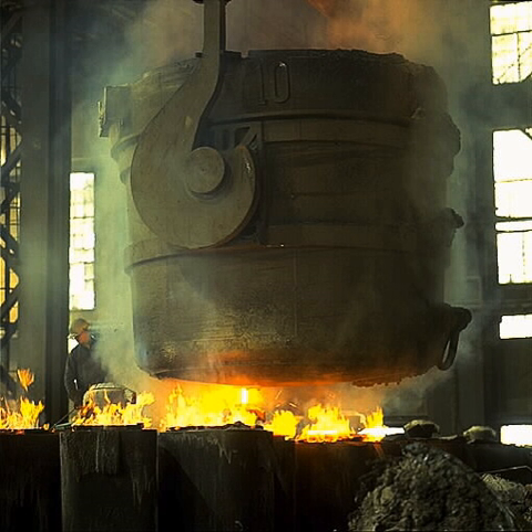Sulfur, largely a contaminant when present, forms iron sulfide, which prevents the formation of graphite and increases hardness. The problem with sulfur is that it makes molten cast iron viscous, which causes defects. To counter the effects of sulfur, manganese is added because the two form into manganese sulfide instead of iron sulfide.